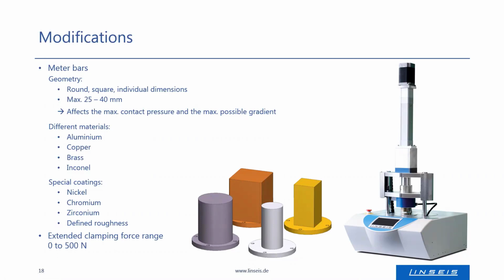The meter bars are available in different materials: aluminum, copper, brass, or for example Inconel. The different materials are optimized for different thermal conductivity ranges, and the standard, which is mostly used for thermal interface material characterization, is the aluminum meter bar. There are also different coatings available for these meter bars: nickel, chromium, zirconium, and one can have a defined roughness.